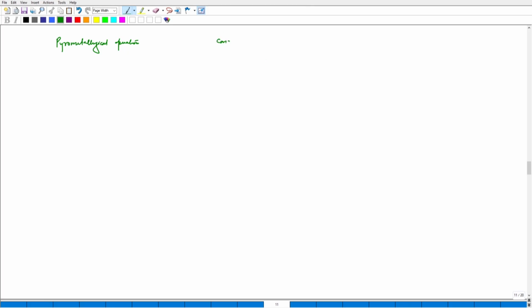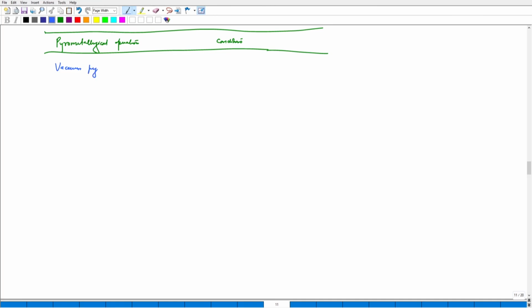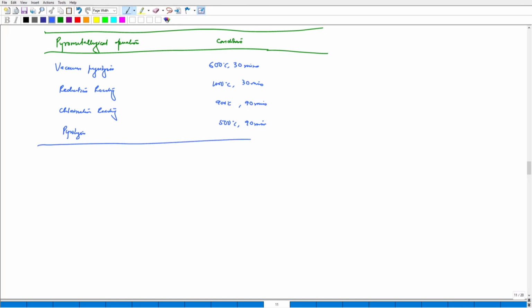and we have conditions. Vacuum pyrolysis, 600 degrees Celsius, 30 minutes. Reduction roasting, so 1000 degrees Celsius, 30 minutes. Chlorination roasting, 900 degrees Celsius, 90 minutes. And we know that in all of these processes we can have some or the other alternative additions also. Pyrolysis, 500 degrees Celsius, 90 minutes. Some of the references are